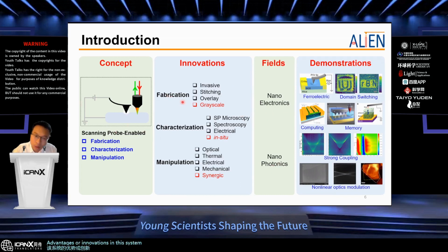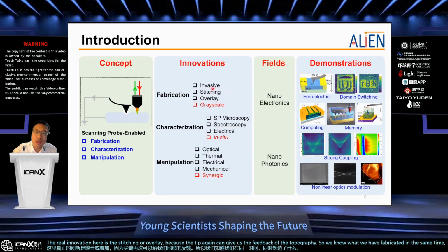The first part is fabrication. Apparently, we can use the thermal interactions, or we can also introduce the laser interaction, the photon interactions, to make nanofabrications. The real innovation here is the stitching or overlay, because the tip again can give us the feedback of the topography. So we know what we have fabricated at the same time, simultaneously. Then we can do the stitching and overlay fairly easily. I'll show you an example. Second innovation in fabrication is the grayscale, because the tip has Z direction control of the height, so we could burn a three-dimensional or 2.5-dimensional grayscale pattern on polymer.